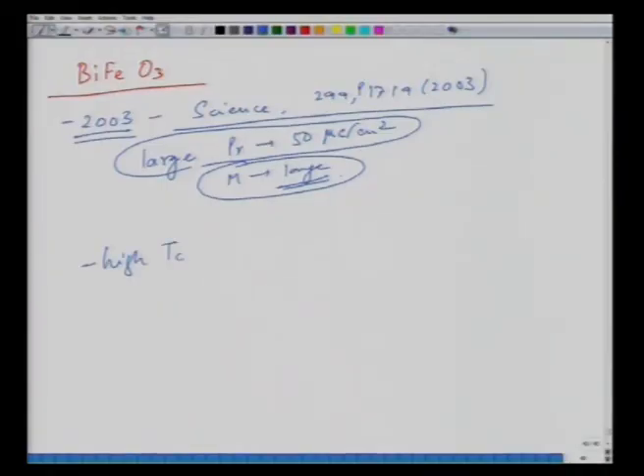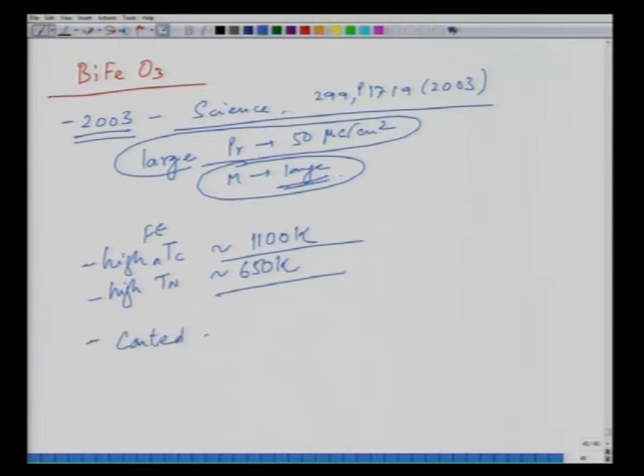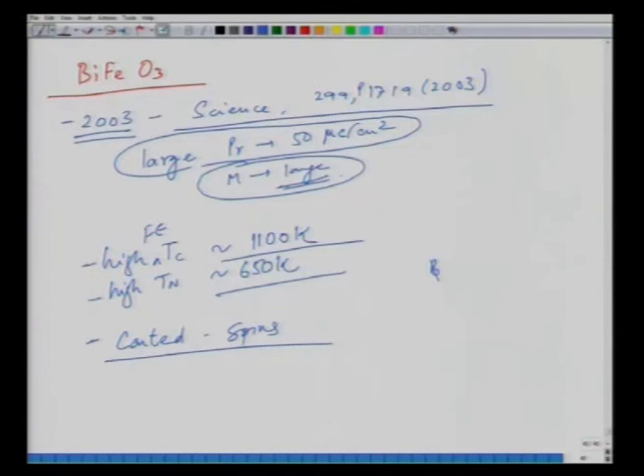tune this material. So this material has a high Tc of around 1100 K, which is the ferroelectric Tc, and a reasonably high TN of around 650 Kelvin, and this is an antiferromagnet with canted spins. Now these canted spins are spiral in nature. As we discussed in antiferromagnetism, your spins are not perfectly antiparallel, rather they are a little bit inclined with respect to each other.